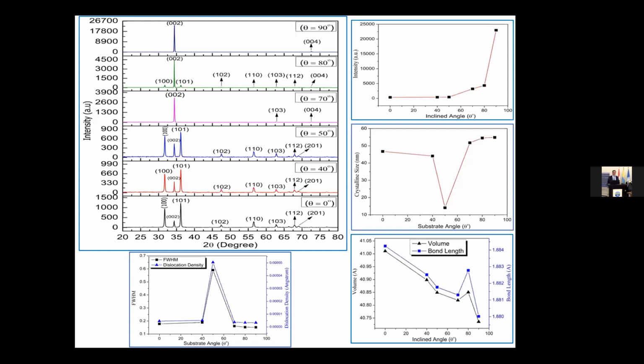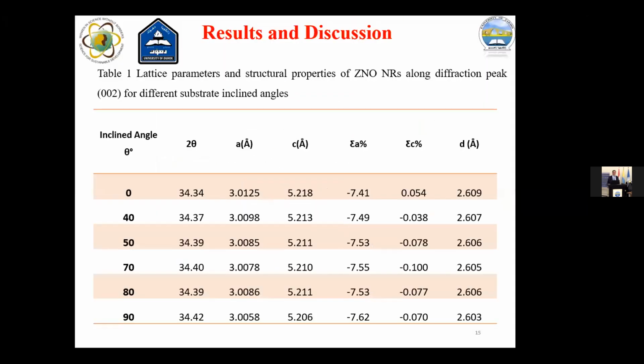Also, the XRD confirms that the substrate inclined angle has a remarkable or significant effect on, for example, the crystal size, the intensity, the volume, the bond length, and the dislocation density. All these parameters change with the change in the substrate inclined angle. Also, the substrate inclined angle changes the lattice parameter of our zinc oxide nanorods and the stress and strain, and we also have tensile and compressive stress in such samples.